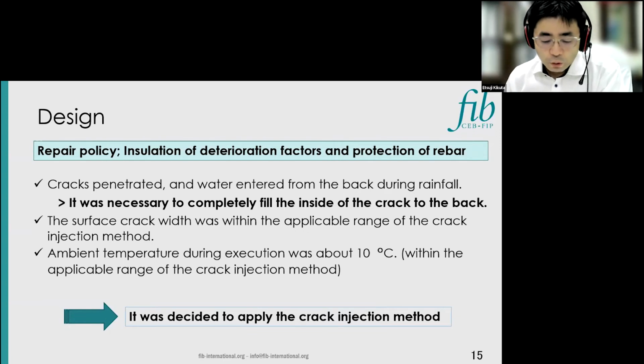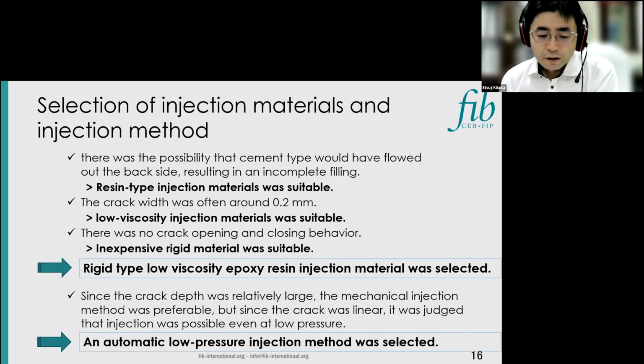Also, both the crack width and environmental temperature were within the applicable range of the crack injection, and the surface blockage could be handled by cross-cutting method. Based on these, it was decided to apply the crack injection method. About selection of injection materials and injection method. Due to the penetrating cracks, cement type could flow out the back and result in incomplete filling. So, resin type injection materials was suitable.